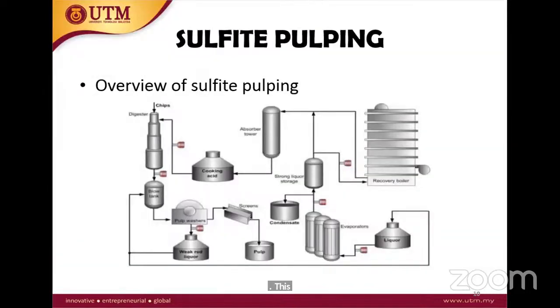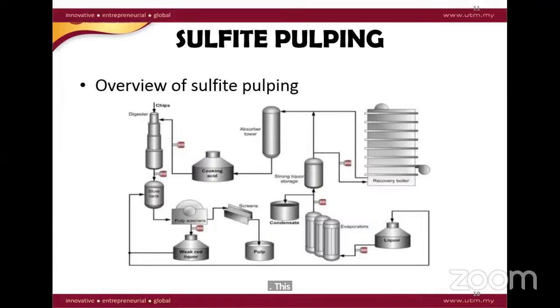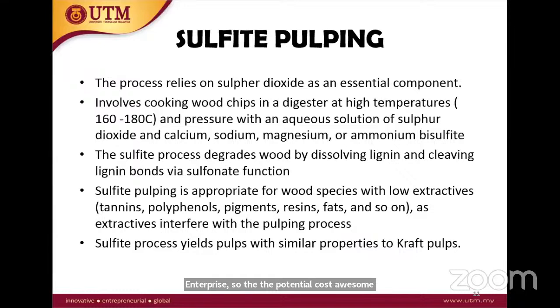This is the overview process of sulfite pulping. For sulfite pulping, the process relies on sulfur dioxide, which is an essential component. It involves cooking wood chips in a digester at high temperature and pressure with an aqueous solution of sulfur dioxide and calcium, sodium, magnesium, or ammonium bisulfite. The sulfite process degrades wood by dissolving lignin and cleaving lignin bonds via sulfonate functions. Sulfite pulping is appropriate for wood species with low extractives, such as tannin, polyphenol, and resin fat, as these interfere with the pulping process. The yield produced from this process is quite similar to that of the kraft pulping process.